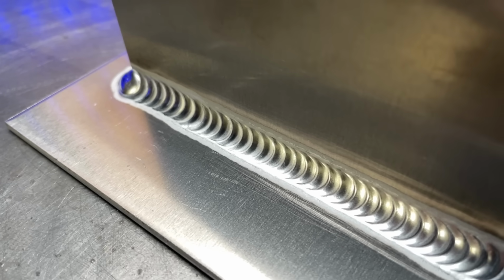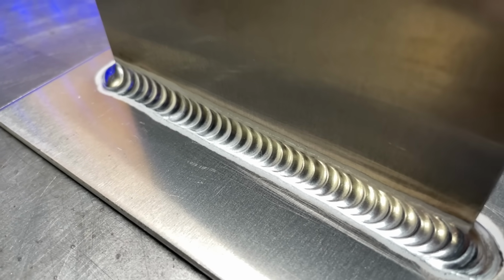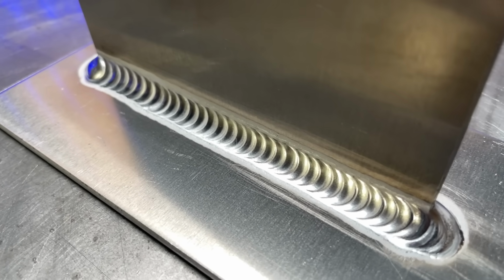Obviously, as long as you aren't getting into amperage which is too high in relation to the material thickness you are using, you're gonna be able to hang out a little bit longer and you can afford to spend some time to allow things to properly establish. This is especially important with joints like a fillet joint or something like that. Those ones in particular are extremely tough and sometimes really grumpy to get started. Spending a little bit of extra time to let things properly develop and establish before moving is certainly worth it with a joint like that.